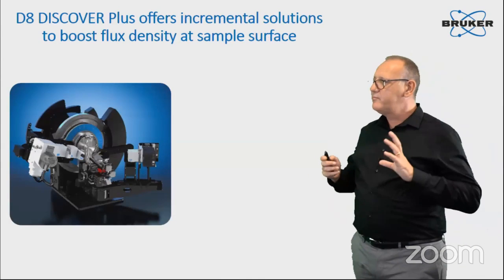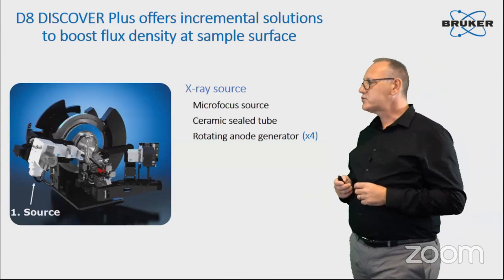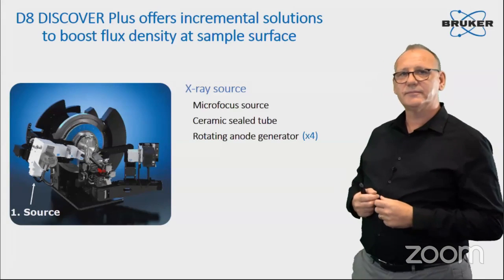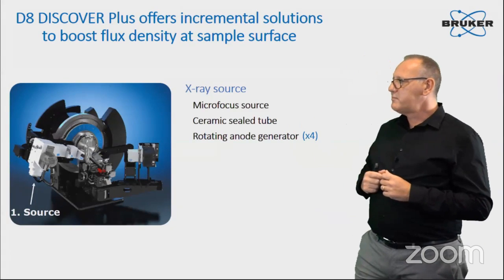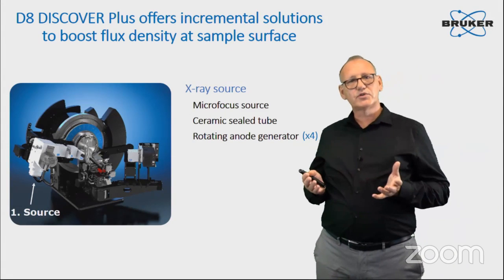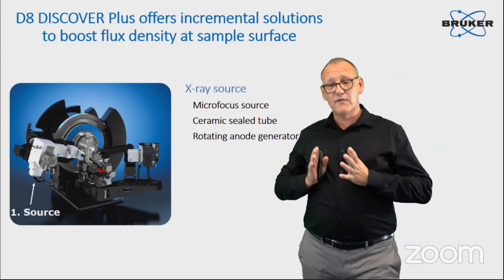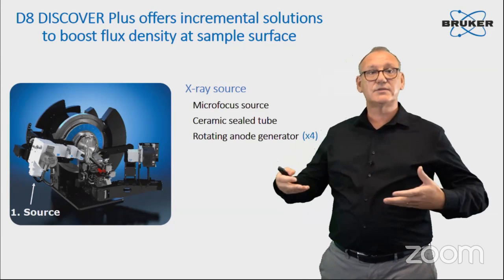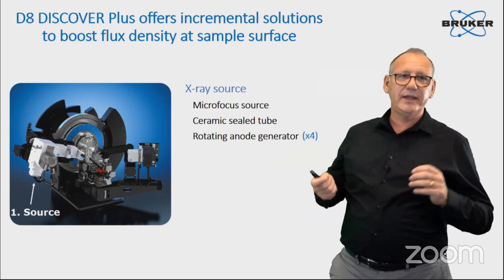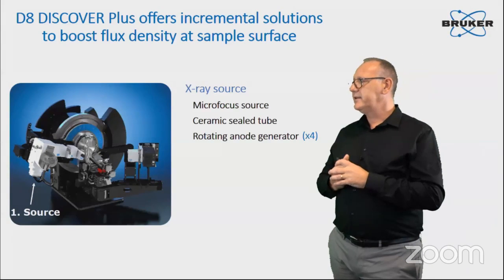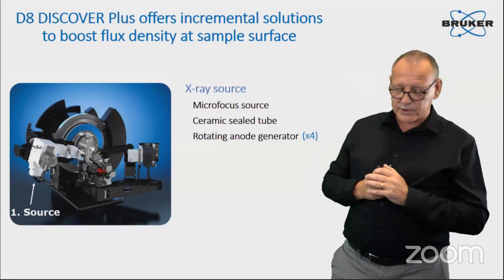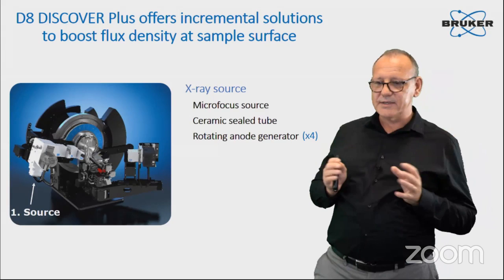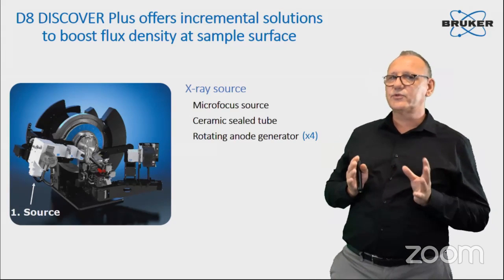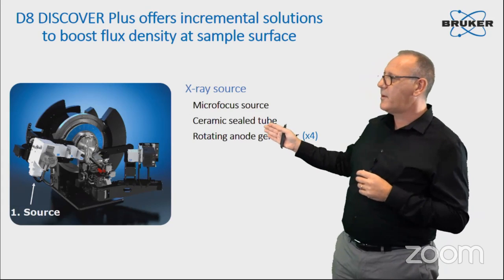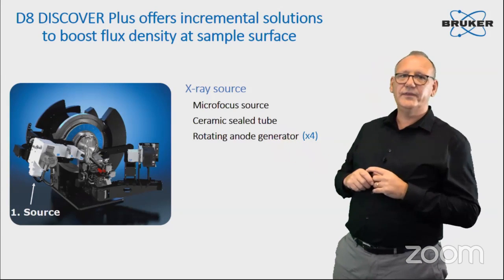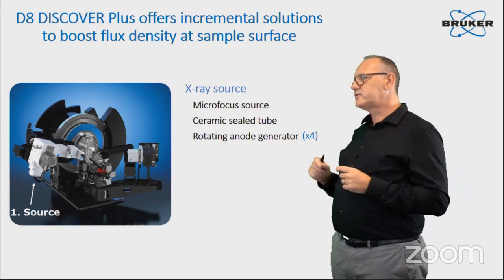So let's see how we can boost a bit the intensity. You have different ways. The first one is, of course, to consider a strong source. A micro source might not be, in this case, the best approach because the micro source has a very low axial divergence. So it has a very good in-plane resolution, but probably a slightly lower flux density than the other sources. What we want to emphasize here is the intensity, and we'll see later we don't really need resolution. So I would rather consider either the ceramic tube or the rotating anode in this case. If you go for rotating anode, you get 4 times more intensity.